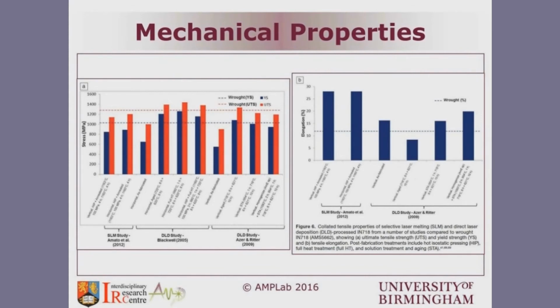Obviously, if you want to make a component, we want that component to achieve the correct mechanical properties. There are some studies now in the literature showing an increasing importance for post-processing methods like hipping, using hot isostatic pressing. The study by Blackwell showed that you can achieve UTS and yield strength exceeding what we get from forgings just by doing a post-processing and heat treatment procedure involving hipping for Inconel 718. This shows that it's in some way a necessity to use post-processing in many applications, just the thermal post-processing in this case.